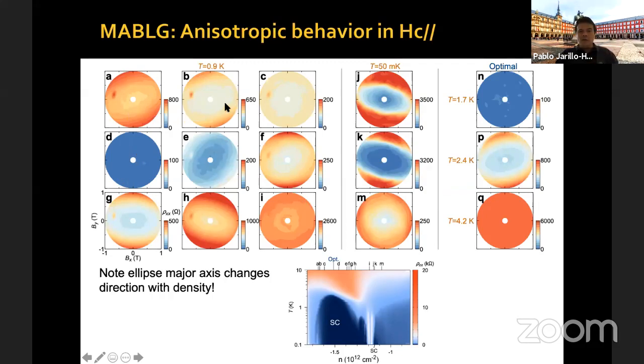But as we go, even at 0.9 Kelvin, as we go around the superconducting dome, these different panels show you the evolution of the nematicity of the critical field, and you can see that you have these ellipses, okay? At base temperature, if we go to regions where we have very small TC, such as J and K here, we can see even at 50 millikelvin these ellipses. At optimal doping, we have to go all the way to 2 Kelvin to see the ellipse, okay? Now, if